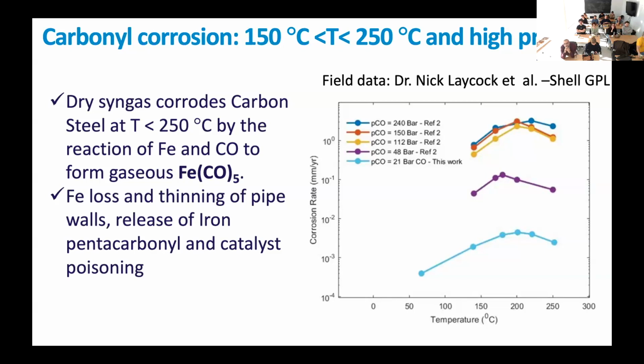As you know, in large petrochemical plants we cannot use stainless steel, it's too costly. So we use carbon steel. And in this case, the reaction of iron and carbon monoxide led to the formation of this gas, which is iron pentacarbonyl. They noticed iron loss, thinning of the pipe, release of iron pentacarbonyl, even if it was a few millimeters per year. But what was actually nasty is that their catalyst was poisoned by the gas. They had catalyst poisoning, which means the catalyst was deactivated because of the gas. And then they shared with us the following figure.